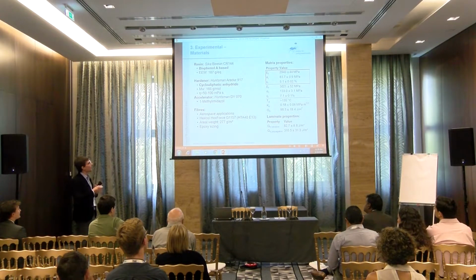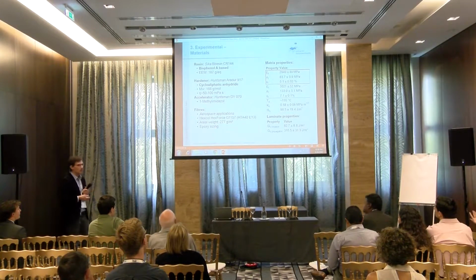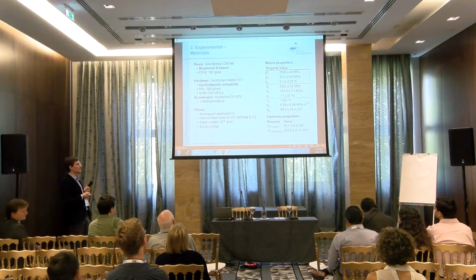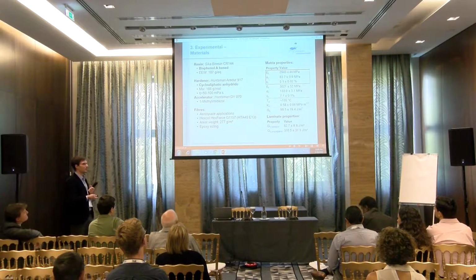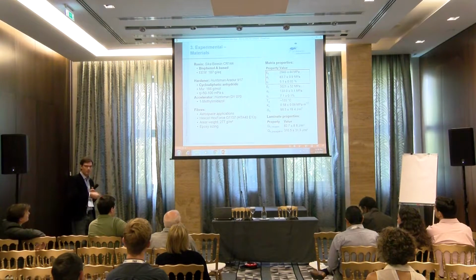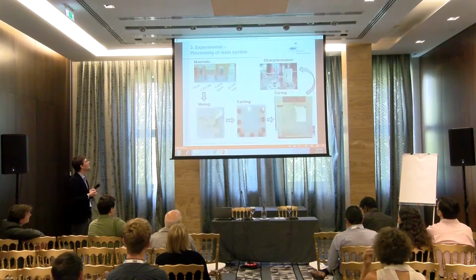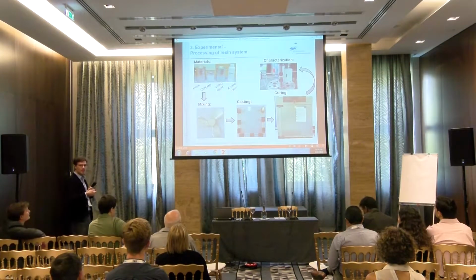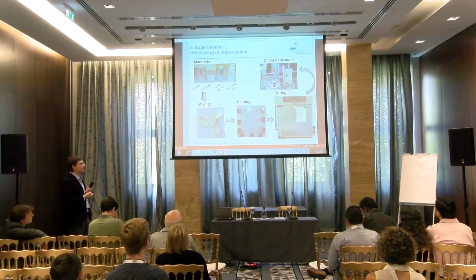Yeah, and I have given some properties of the neat matrix, where you can see it's quite a brittle system, which has already quite some elongation in the unmodified version. Where's the fracture toughness? There. So 0.6, which is far away from 450 megapascal, what we heard in the morning as well from Professor Ricci for metals. So what happened? We mixed the materials, cast them in glass plates, obtained our samples after curing them in the oven, and characterized them via different methods.